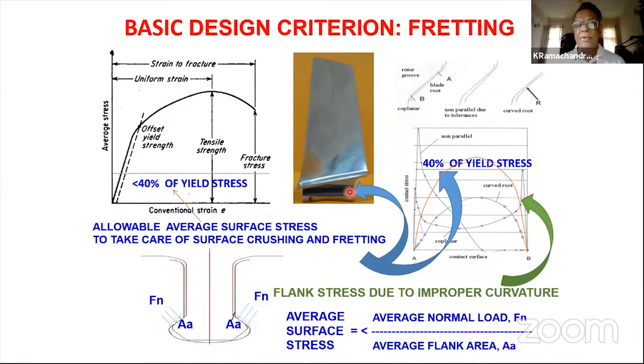And we don't understand fretting very properly because it involves coefficient of friction, temperature, and the sliding velocity and so on. We ignore that because of ignorance. We have a fudge factor or ignorance factor. We are now designing these parts, these locations here on empiricism and experience-based numbers. And the idea today is if you have a design stress here, which is less than 40% of the yield stress at that point, at the temperature, we are supposed to be safe and avoid fretting fatigue.